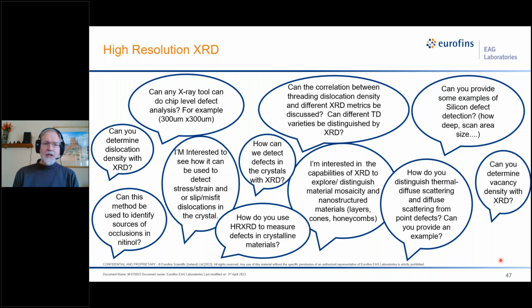Defects and dislocations will broaden these peaks. Sometimes this is implant damage, sometimes it's strain in the crystal causing it, sometimes it's mismatch between the substrate and the film, which causes the film to be under high stress, and it will create dislocations to relieve that stress. But basically what you're going to do is measure the width of the peak, subtract out the instrumental resolution of the peak, and the broadening that you get is going to be a function of the dislocations. All right, Stephanie, back to you.